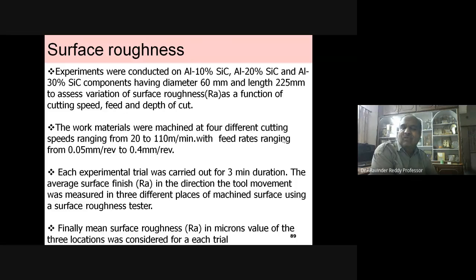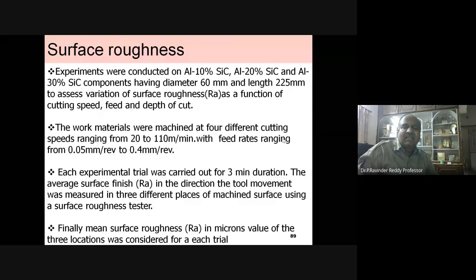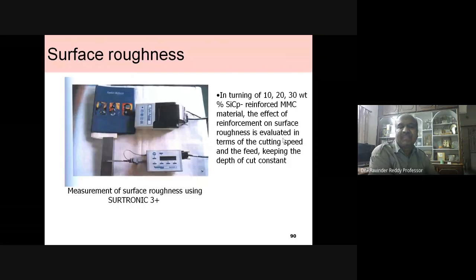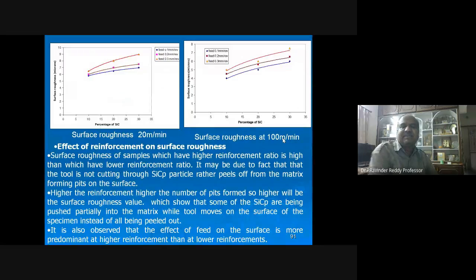Each experimental trial was carried for 3 minutes duration. The average surface finish in the direction of the tool movement was measured in 3 different places of the machined surface using a surface roughness tester. Finally, mean surface roughness in microns of the 3 locations were considered for each case. This is surface roughness measured using Surtronic for turning of 10, 20, 30%, as I mentioned.